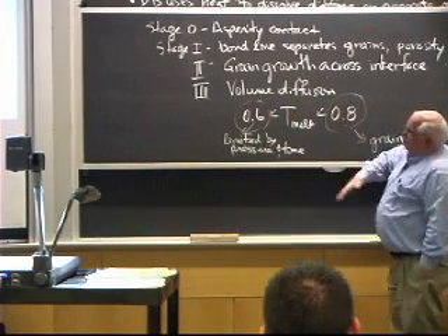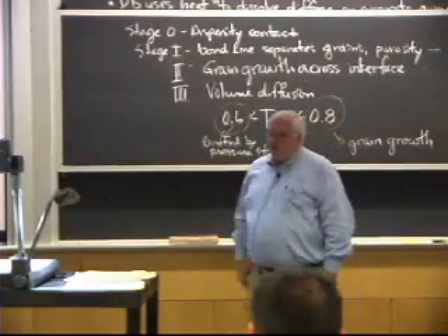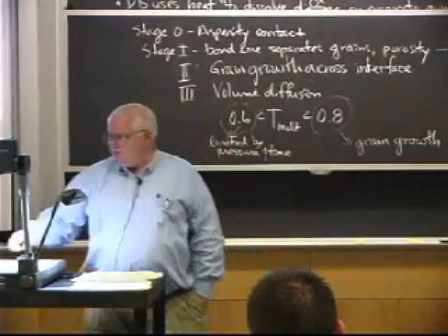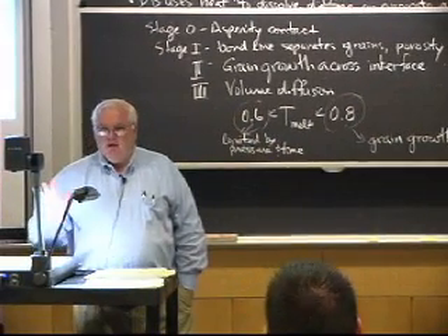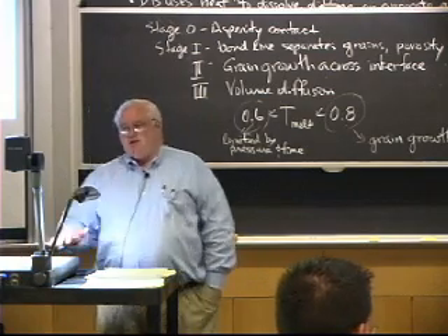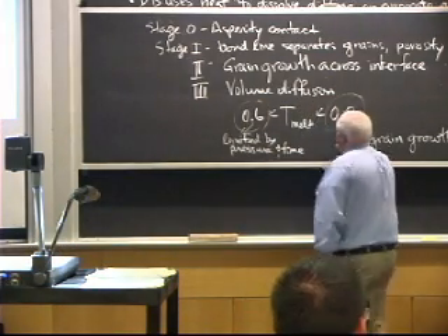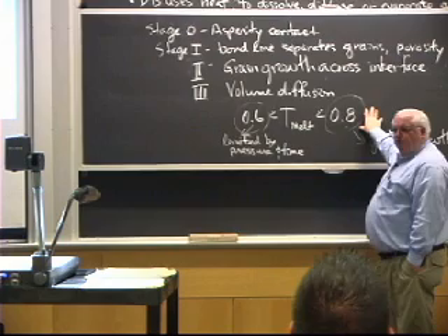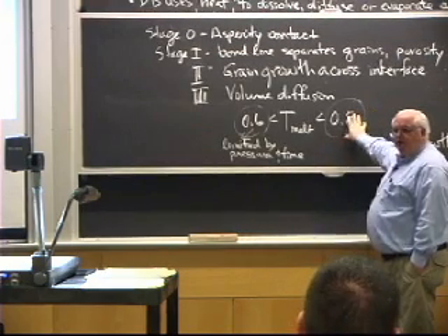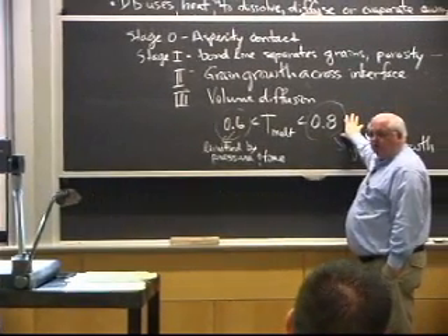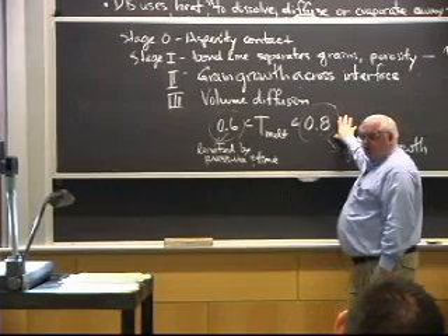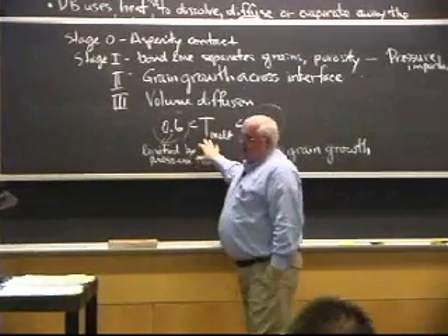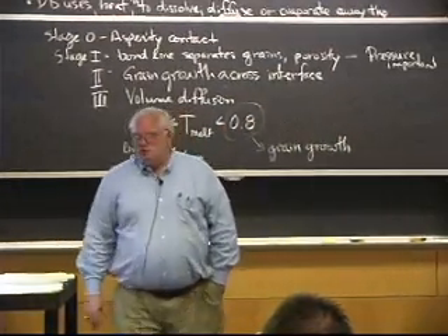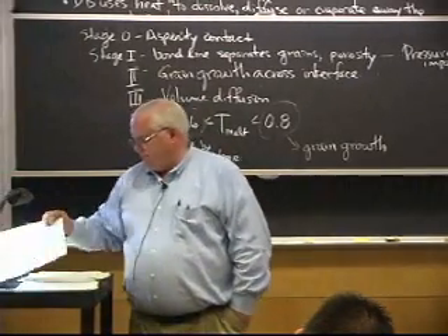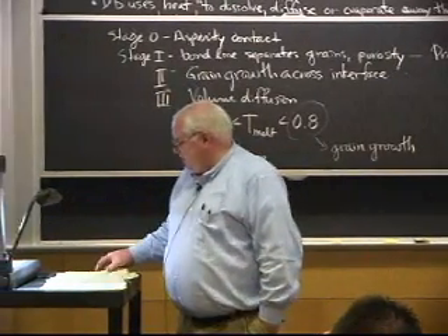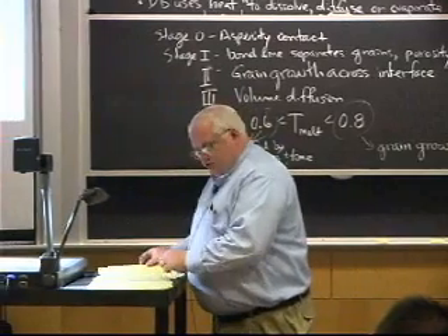So once I get to the point where the grain boundaries have swept past and left behind volume porosity, then the process is over. And it turns out grain growth occurs quicker at higher temperatures. And so I don't want to push too high in temperature, or I'm going to get to stage 2 and stage 3 before I want to, and I'll leave too much porosity at the interface. So it turns out you've got a fairly narrow range of processing temperatures, and that limits the process. Okay? So that's diffusion bonding.